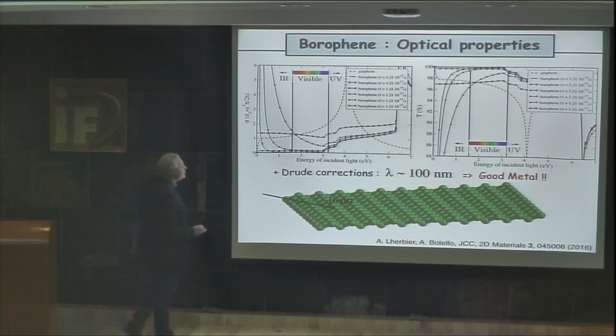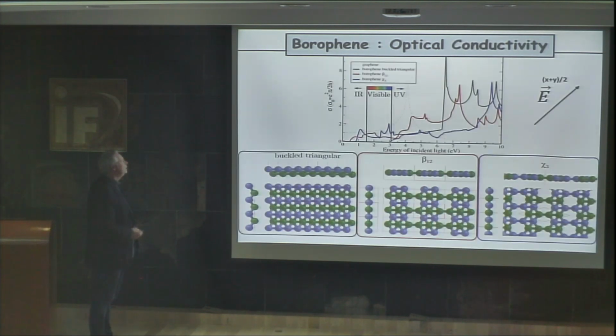This is quite surprising, but the point is that for a value which is the case for good metals and which could potentially be attributed to Borophene, we should normally have 100% transmission, which is clearly higher than what you can observe in graphene, for example. We have also checked the two other phases that are quite stable, and we also observed, well, it's not so great, but we still have a better value for the transmission compared to graphene.